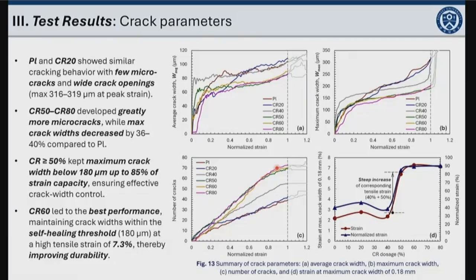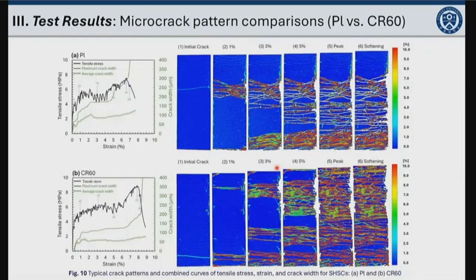This is the typical microcrack pattern comparison between the plain and CR60 samples. As compared to the plain sample, this is the plain sample, by incorporating the crumb rubber, the maximum crack width was more effectively controlled, especially in the strain hardening zone.